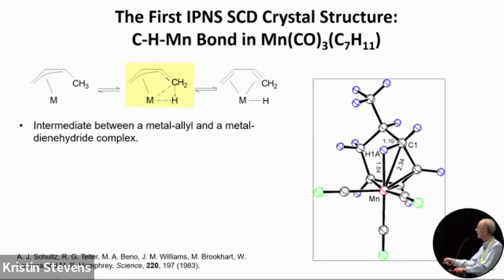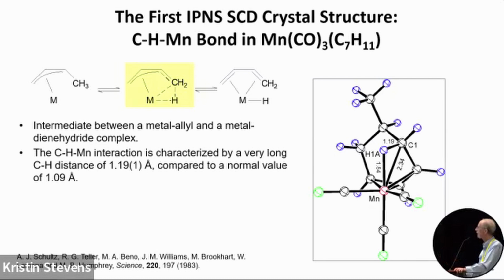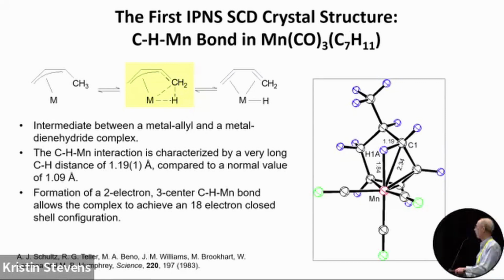So the molecule is actually an intermediate between a metal allyl, shown here, and a metal diene hydride complex, shown here. So here's the hydride. So essentially, we're extracting an H atom from a CH3 group and forming a metal hydride. The carbon, hydrogen, and manganese interaction is characterized by a very long CH distance of 1.19 angstroms compared to a normal value of 1.09. And with the 2 electrons in the CH bond, we have the formation of a 2-electron, 3-center CH manganese bond, which allows the complex to then achieve an 18-electron closed shell configuration, which gives it its stability. That's why we can see the intermediate here.